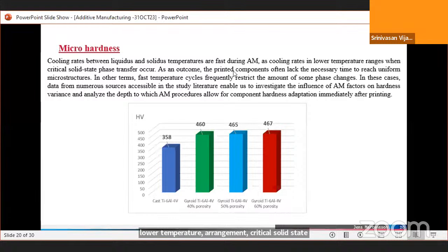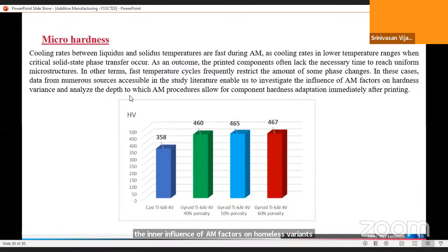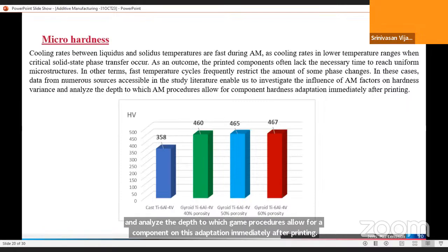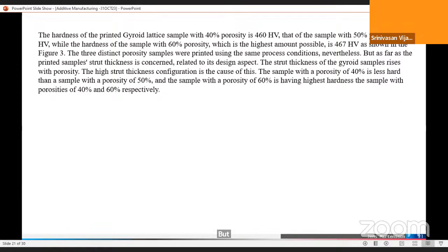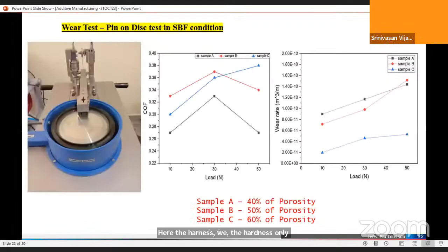As an outcome, the printed components often lack the necessary time to reach a uniform microstructure. That is, fast temperature cycles frequently restrict the amount of some phase changes. In these cases, data from numerous sources accessible in the research literature enabled us to investigate the influence of AM factors on hardness variants and analyze the extent to which AM procedures allow for component hardness adaptation immediately after printing. But here, I have given the hardness only. As well, we did a pin-on-disc wear test. In the previous case, we did a fretting wear test.